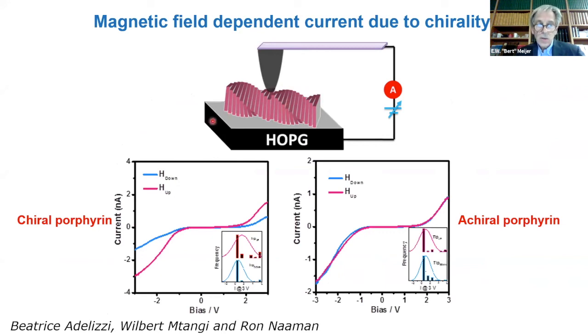And what you see here, this is the setup: you measure conductivity through this device with a magnetic field in one direction or in the other direction. And then you look at the differences. With the chiral porphyrins, you see there's a difference between magnetic field up or down, while with the achiral porphyrin, it is the same in both cases. So the achiral porphyrin gives you equal amounts of P and M helices, while the chiral only gives you one type. That means that this cartoon is actually incorrect. You look at a bundle of fibers.